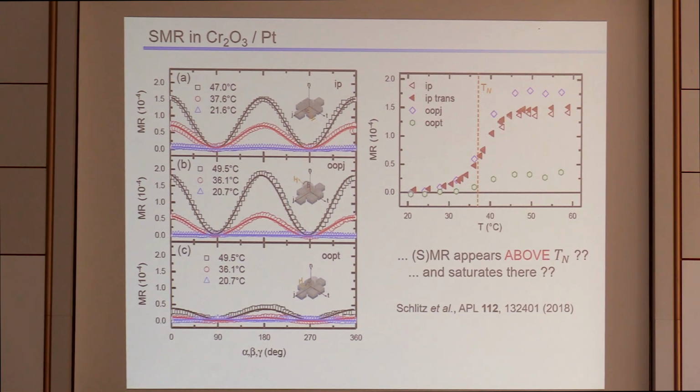Well, we tried to measure the field dependence. It seems to saturate. You tell me what the typical paramagnetic response of that system should be. I would expect that is pretty Brillouin-like. That seems not to fit, but our data sets are not good enough to really draw robust conclusions in this direction. One can look directly at susceptibility, right? Like a complement. Yes, but this is a thin film, so susceptibility is really, really difficult because you have a substrate beneath which essentially blurs everything that you'd like to extract.